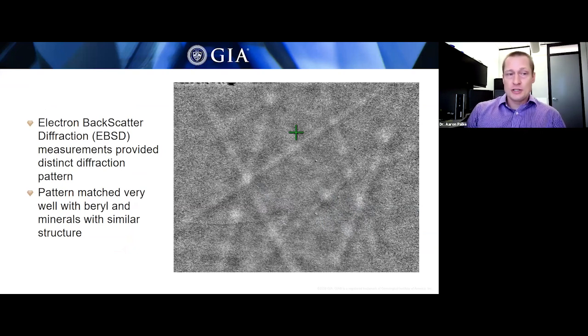Now, the first thing we did was this technique called electron backscatter diffraction. And this is very similar to what Evan Smith mentioned about the X-ray diffraction. But instead of X-rays, we're using an electron beam. So when you shoot an electron beam at the sample, the electrons can actually act like waves, just like X-rays can. And so those waves that we hit with the electron beam onto the sample, they diffract off of the different crystalline planes within the material. And each material, because it has a different mineral, because it has a different unique set of crystallographic planes in it, it gives off its own unique fingerprint in the EBSD analysis.